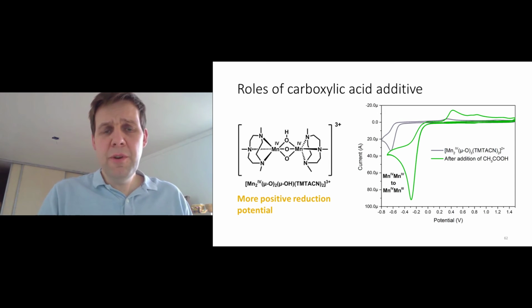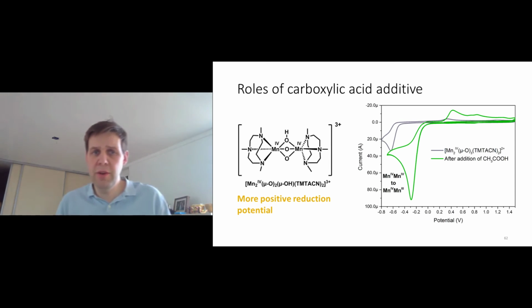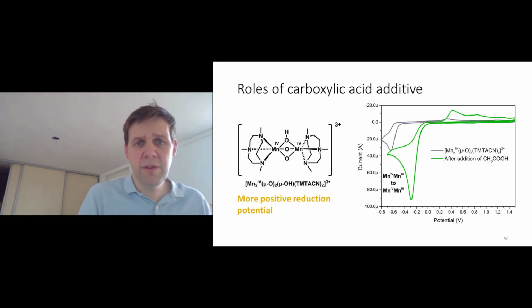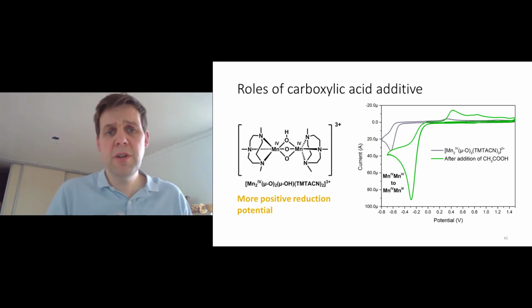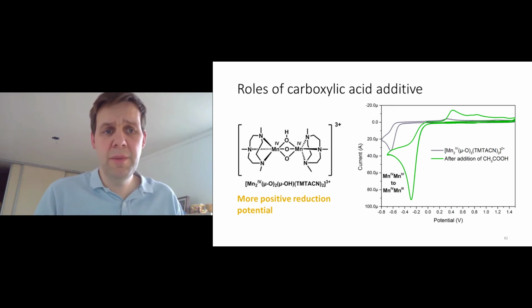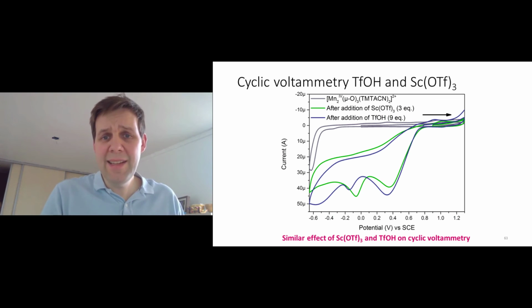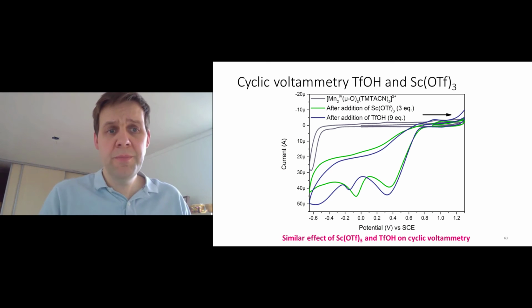And actually the 4,4 complex is kinetically very inert. You have to reduce it to a 4,3 or a 3,3 oxidation state before you start getting ligand exchange and you can form an active form of the complex. Triflic acid and scandium triflate have exactly the same effect on the redox chemistry of the catalyst. In fact, it makes it much easier to reduce.